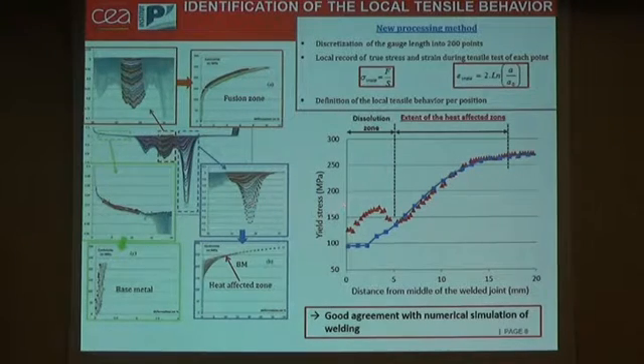And here, in the first approach, we compare our results, the evolution of the yield stress along the welded joints, with the numerical simulation of welding. And as we can see, we have a good coincidence between the two results, except in the dissolution zone, and this is due to the fact that the numerical simulation does not take into account the natural aging that may occur after welding.